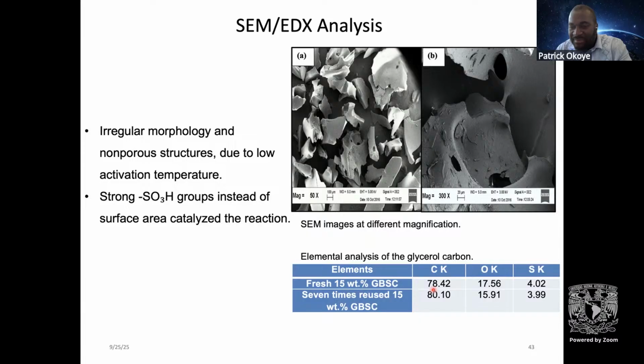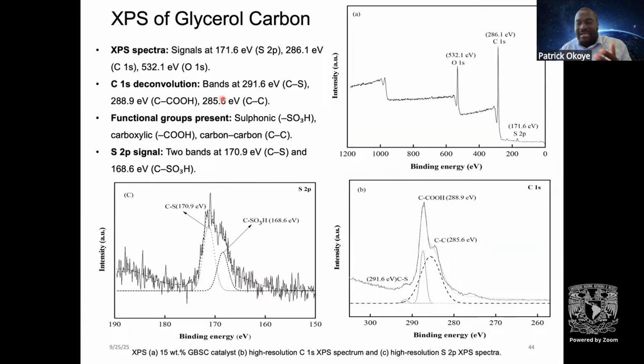When we produce this material, we also found that we have a carbon-rich material. And after using this material 7 times, it did not degrade or deactivate. In fact, we continued production for over 10 recycles without any problem. So we tried to characterize this material. We looked at the XPS of the material, that is X-ray photoelectron spectroscopy. We found the elements sulfur and carbon, and also some sulfonic groups, of course, due to the sulfur. We have the carbon-carbon chain and the carboxylic groups. These groups are very essential in propagating our reaction, and eventually we had a very good reaction.